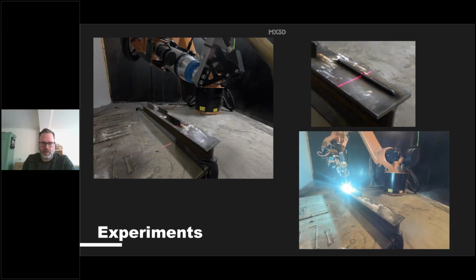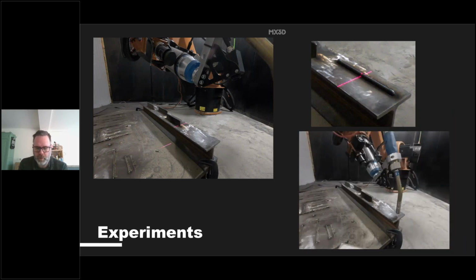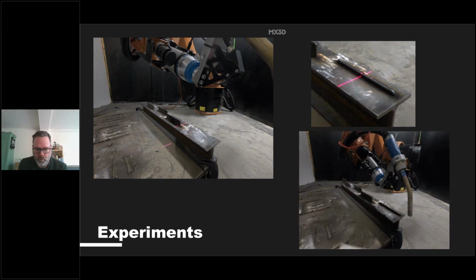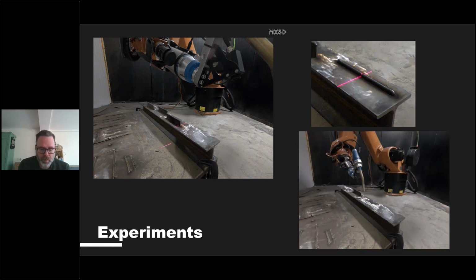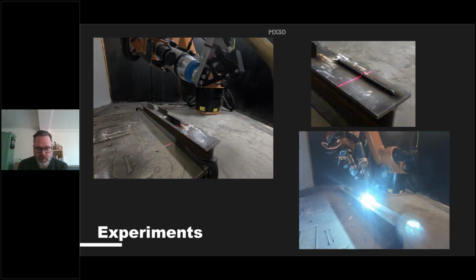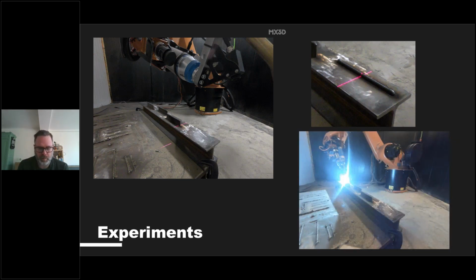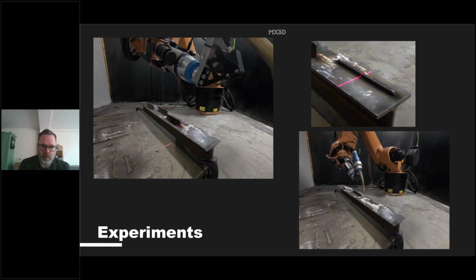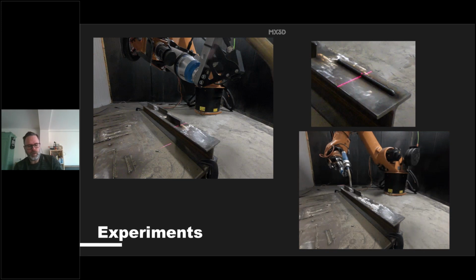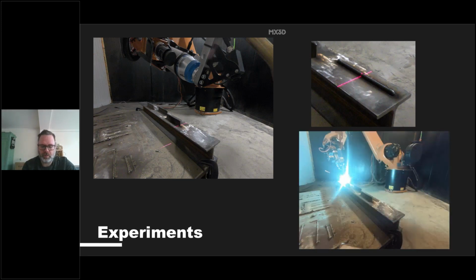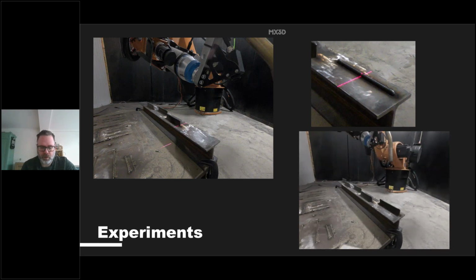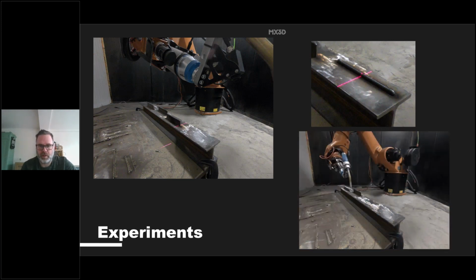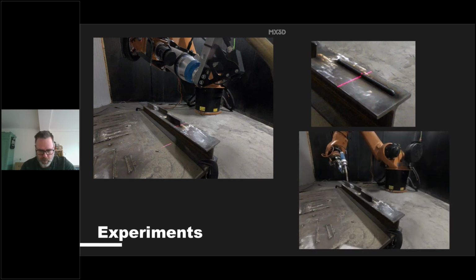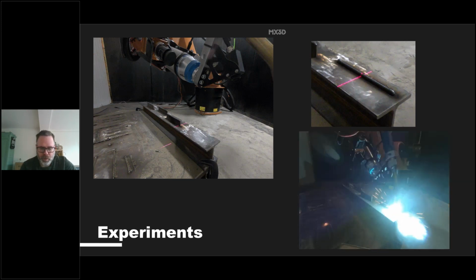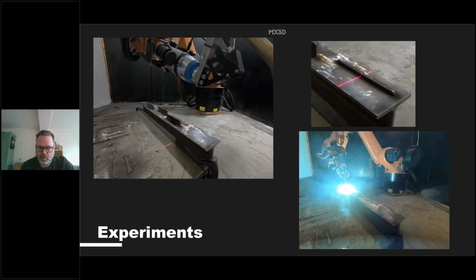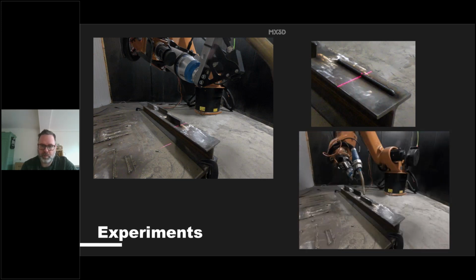A procedure has been developed that takes a configuration file that defines how the experiment should run: the parameters to be varied, the ranges, the step sizes, as well as the number of layers to be printed, the desired interpass temperature, and so on. The desired welding parameters are communicated from the industrial PC to the robot, which in turn controls the welding machine on the fly and sets the desired wire feed speed, for example. Then the operator points the robot to the starting position on the substrate, and the process runs automatically.